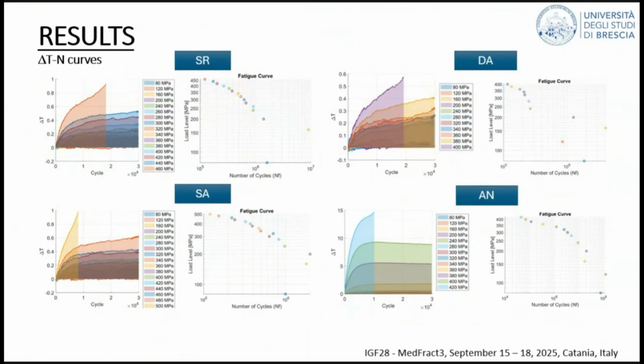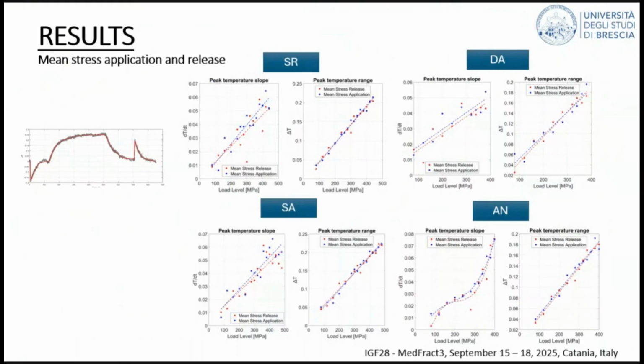So if you assume that this postulate is true, then you can plot a stress life curve, and you can compare it with a conventional one, which I did not report here, but again, you have a good correlation for high stress, and the two curves instead generally diverge when the stress level is low. So I'm approaching the conclusion. I don't know if I have time to show you this final slide.